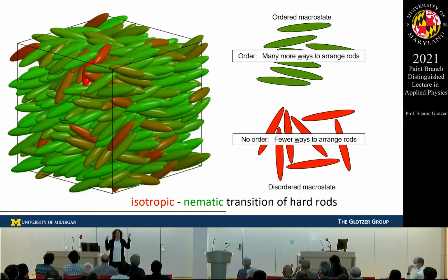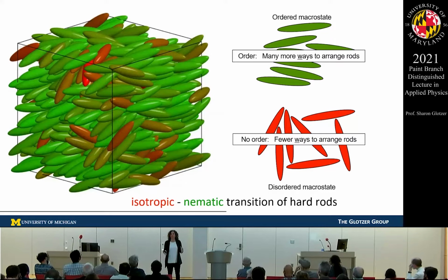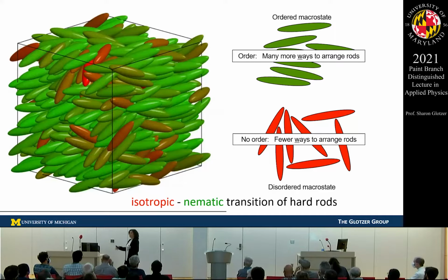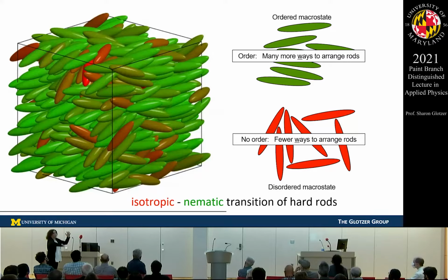So these simulations are at constant number of particles, constant volume, constant temperature. So the relevant thermodynamic potential for the system is the Helmholtz potential, which is the potential energy minus T times the entropy. So without potential energy, you only have entropy. So minimizing the free energy means maximizing the entropy. And the system maximizes the entropy by organizing itself, because there are more ways to arrange these rods if they align than if they don't align, right?